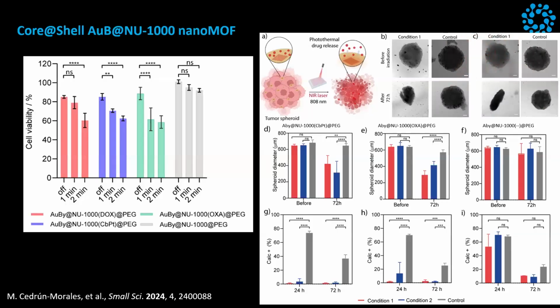After irradiation, we want to destroy the tumor. And this is something that he achieved and demonstrated by looking at the spheroid diameter, how big it is, and then measuring the amount of live cells that remain after the treatment and the release of the carboplatin in this particular case. Okay, so he demonstrated that with this MOF, they can penetrate inside a model of a solid tumor, not because of heat, because if you don't put the drug, you don't destroy the tumor. You need the light and the drug.